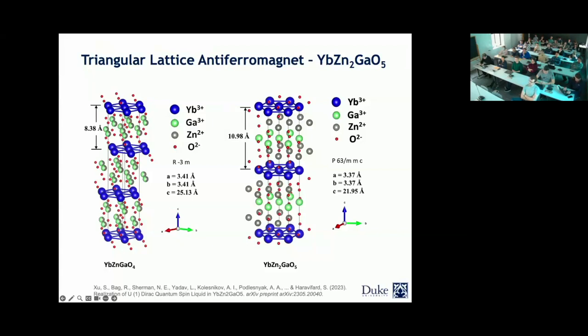What we have done is deliberately put a zinc oxygen layer in between these two layers. By doing that, we gave each element, gallium or zinc, its unique Wyckoff position, and we changed the space group as well. In this way we were able to eliminate this 50% site mixing, so that we would have a clean compound to study and extract the physics out of. I'm going to call this ytterbium zinc 2 gallium oxygen 5, which has an additional zinc oxygen layer compared to the 1114 compound, a 1215 compound. So we have a 1114 with chemical disorder, and a 1215 compound without chemical disorder.